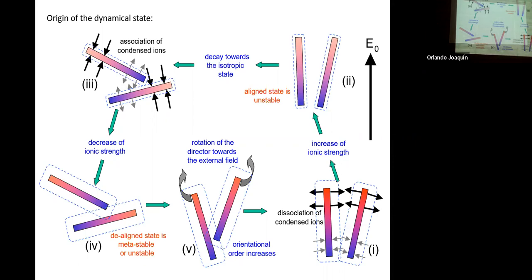Then you have this peeling off of the dissociation of condensed ions. This dotted line here indicates the thickness of the electric double layer. So you peel off these ions, and the thickness of the electric double layer will decrease, because you increase the total concentration in the solvent. So the effective concentration of the rod will therefore decrease.